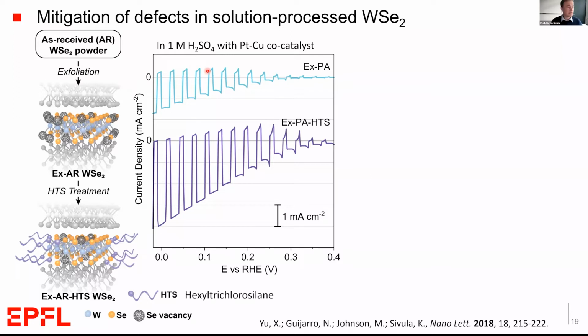In multi-flake photocathodes made and tested in 1 molar sulfuric acid with the platinum co-catalyst, we can see the effect of adding this HTS increases the photocurrent by about a factor of 3 or 4. So we're getting photocurrents here now on the order of about 4 milliamps per centimeter squared. That's a lot smaller than the 25 milliamps that the single crystal was giving.